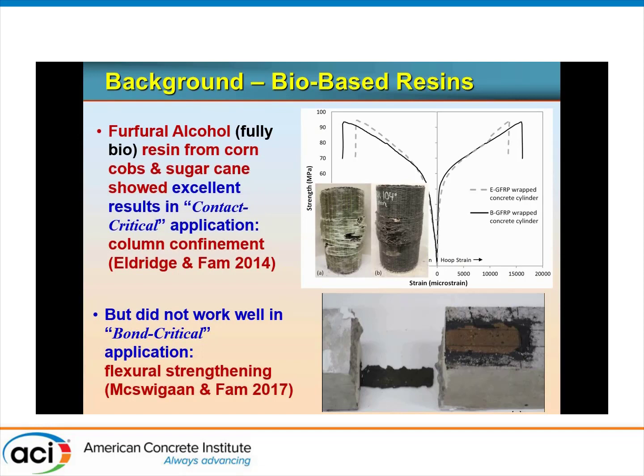So we were quite puzzled. The reality is that it turned out that this particular resin bonds very well to itself. So when you have a wrapped cylinder, you have the overlap and it's bonding very well to itself. But to concrete, it was a different story. We were quite ambitious. We thought 100% bio. Okay, that was great, but it didn't work out. So we started looking into other types, and perhaps reducing our expectations to partial bio or blends with epoxy, as opposed to fully bio.